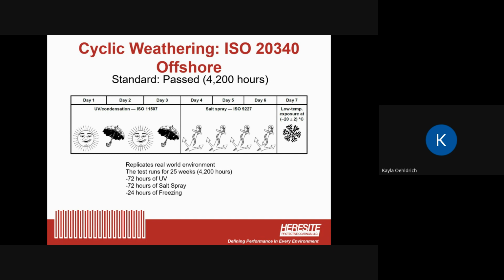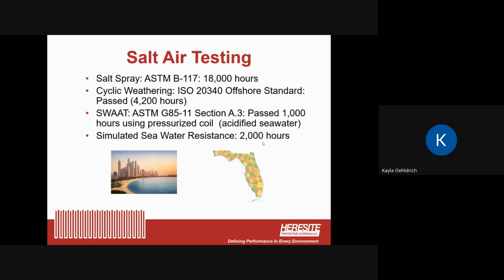So we think this is really important in determining how our products will perform in the most difficult coastal and offshore environments. So we have a few other tests that we do other than the salt spray and the cyclical weathering test. There's a SWAAT test that's used. That's basically using acidified seawater rather than just regular salt water. And then we have a simulated saltwater resistance test also, which is at 2,000 hours for our P413 baked phenolic epoxy. But I don't know anybody that's got 4 tests that they do for salt air testing. Most companies send their panels off to third-party companies, and they do the ASTM B117 test, many of them without scoring it in the middle, and that's their standard. But we have to have more because our customers are more demanding.